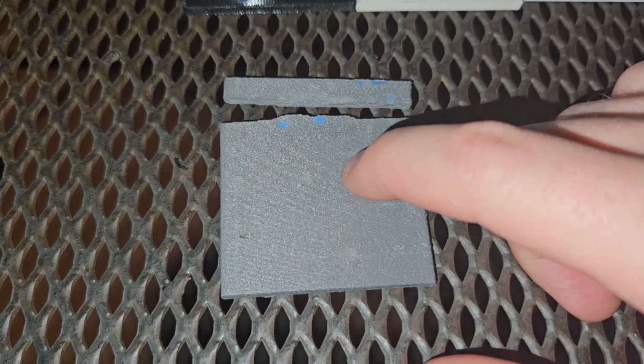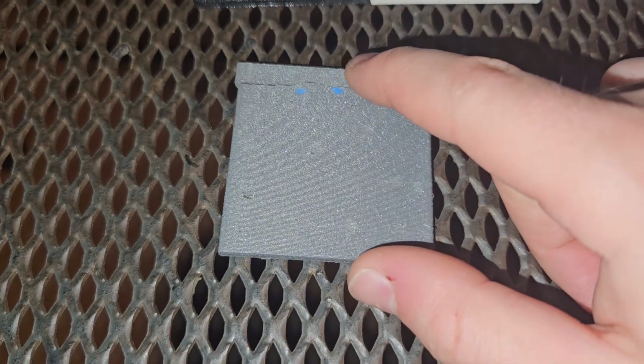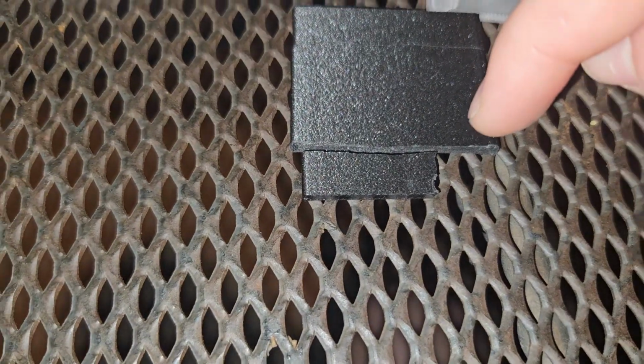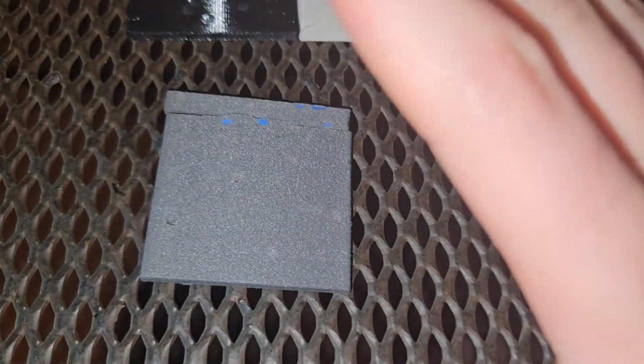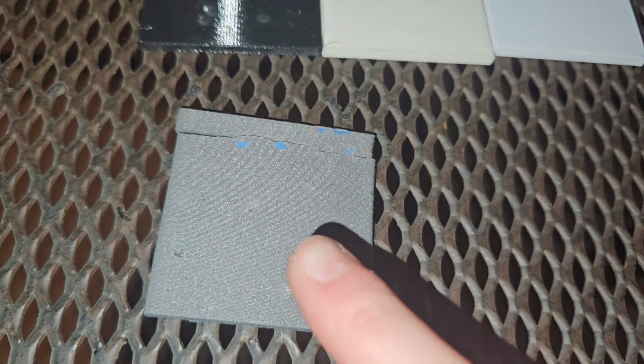It broke mostly along the layer lines and only in one place after a good couple shots, whereas the polycarbonate broke after only 5, and it broke in at least 3 places. I will still call this a pass.